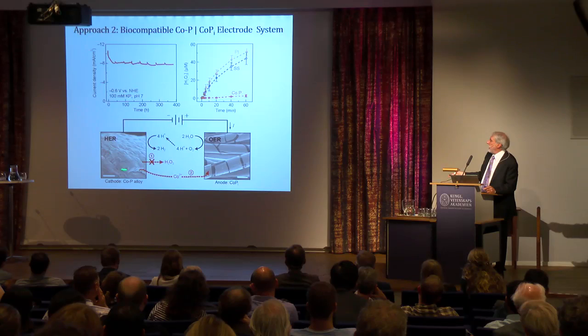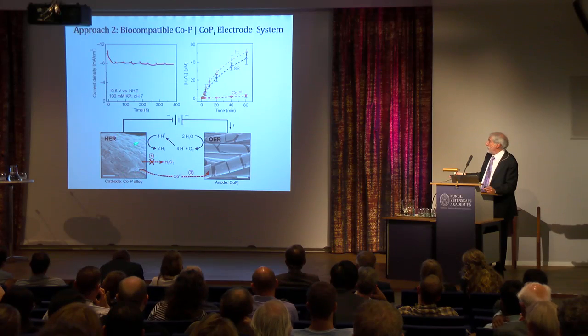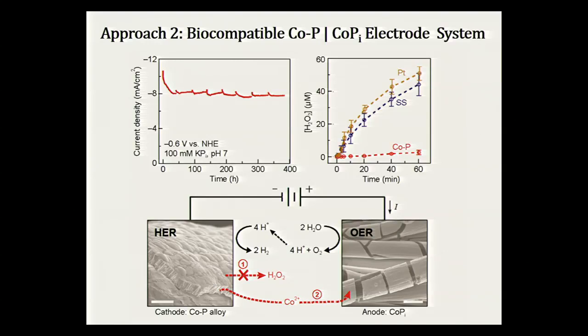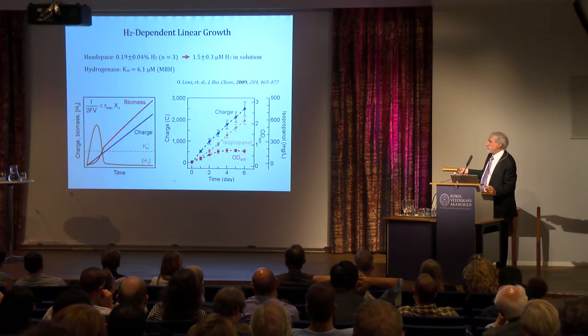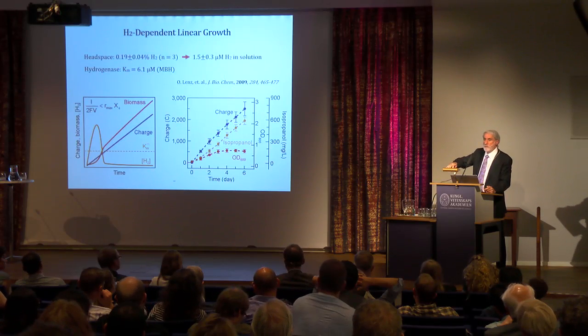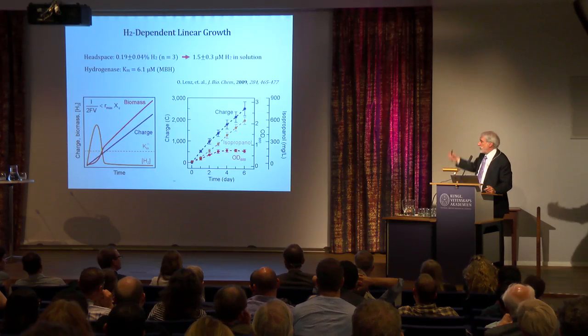We made a different catalyst on the hydrogen side. This is cobalt with a phosphorus alloy, and that catalyst doesn't make superoxide. So these catalysts and my other catalyst made superoxide. This one's making no superoxide that gets translated to H2O2. If I use this catalyst system, cobalt phosphate and cobalt with the phosphorus alloy, the bugs are perfectly happy. That allows us to drop way down in voltage, near 1.2 volts. That ups my overall efficiency.